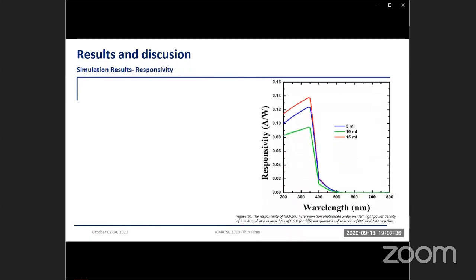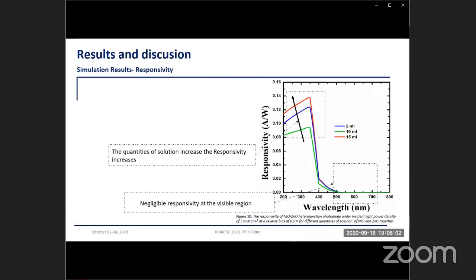The responsivity. The responsivity of a photodetector is an electrical current divided by the incident optical power. By looking at this figure, the device detects in the UV region, therefore negligible response in the visible region. It has been observed that as the quantity of solution of zinc oxide and nickel oxide layers increases, the responsivity also increases. The peak of responsivity increased from 0.09 to 0.14 ampere per watt. The results help us to understand